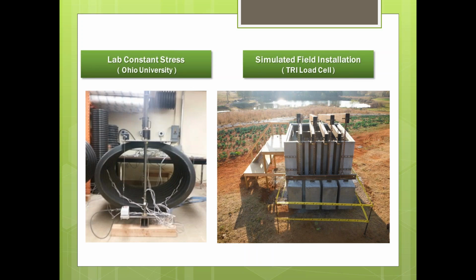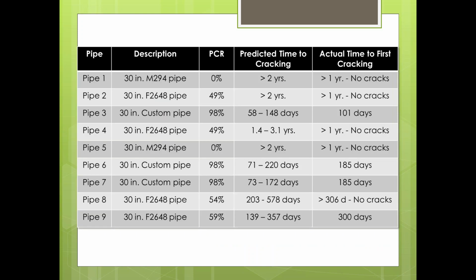Concurrently, there was a series of pipes that were actually studied in simulated load cells, actually buried in soils with stress plates and significant amounts of stress being placed on that actual soil loading and column itself, to give an even more representative sample set of a true buried condition with confining stress on the sidewalls of the pipe themselves too. So I'm going to talk primarily and show some of the data that was done with the field testing in the actual load cell itself, which is probably the most representative of stress levels in the field.